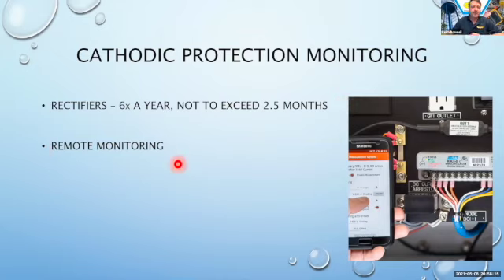At VMT, LESCA actually utilizes a remote monitoring system that continuously monitors these rectifiers. And they have limits set, upper and lower limits. So if they don't have power to that rectifier, that remote monitor recognizes that and sends an alarm to the corrosion personnel there at LESCA. They're made aware of it, and they can investigate why there's no power. Likewise, if it falls out of tolerance of their lower alarm limits, or exceeds their upper, it gives them another alarm in which they can investigate further. So it's a great tool to have for monitoring purposes, and it's very, very effective.